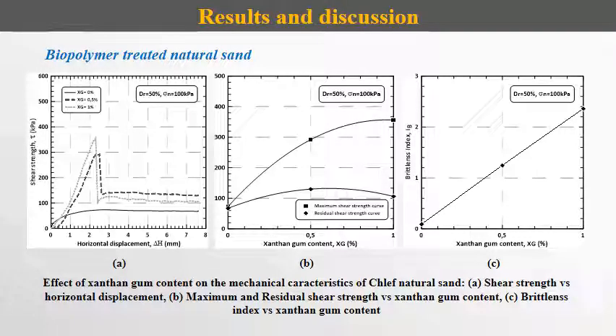Cheng et al. in 2019 attribute the strengthening effect to a condensation and aggregation effect of high tensile xanthan gum gels between sand particles. The maximum shear strength increased proportionally with the increase of gum content. In addition, the residual shear strength of Chlef sand increased when biopolymer treatment was applied. The residual shear strength of biocemented sand at 0.5% was almost 2 times that of natural sand.